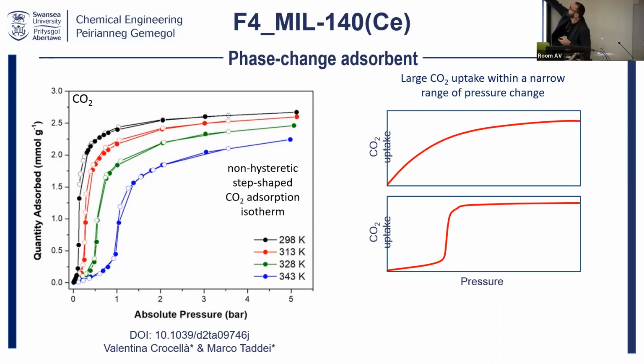Here I have two curves showing the pressure of the CO2 and how much CO2 is captured. One is the standard isotherm, also called Langmuir, for example, and one instead is this S-shaped isotherm. I want to show you why all these discussions so far. We have two pressures now. One is the pressure of adsorption, the pressure I use to get the CO2 on the material, and a pressure of desorption, the pressure that I use to remove the CO2 from the material.